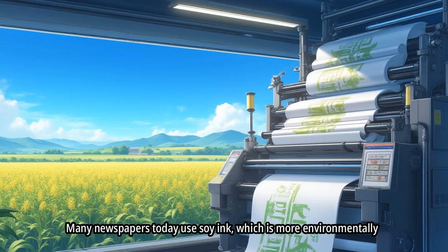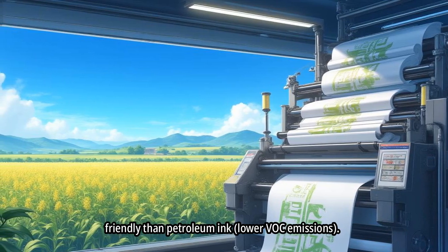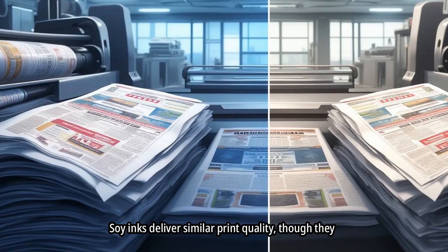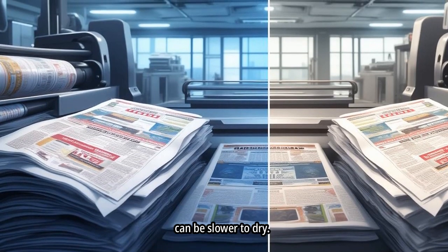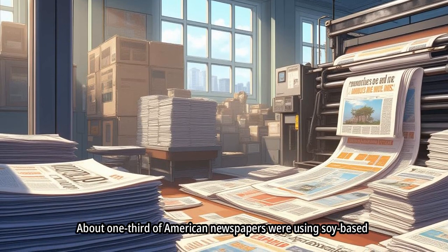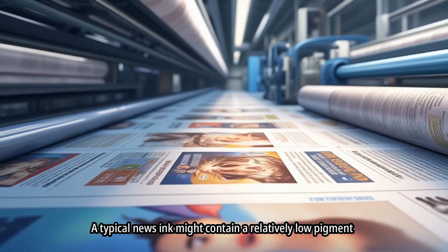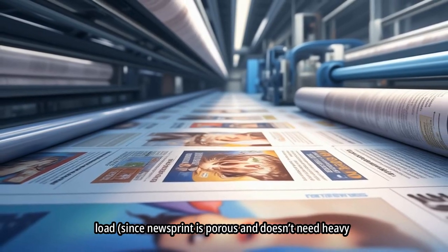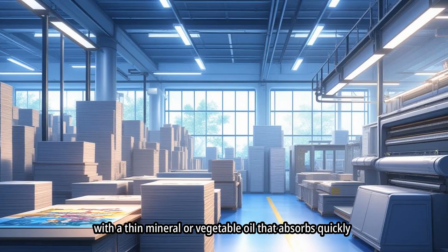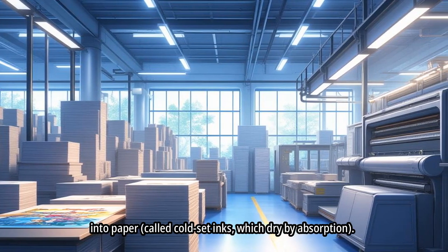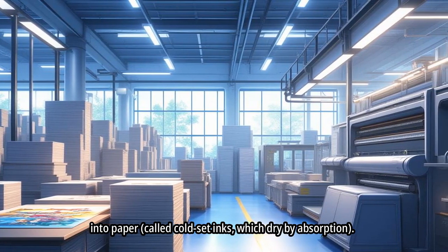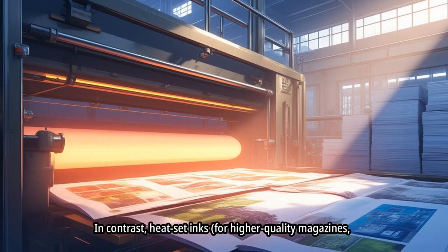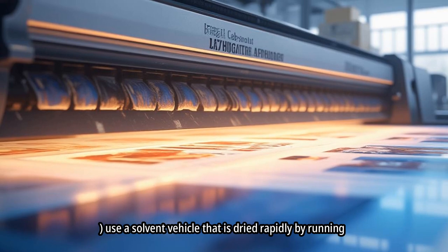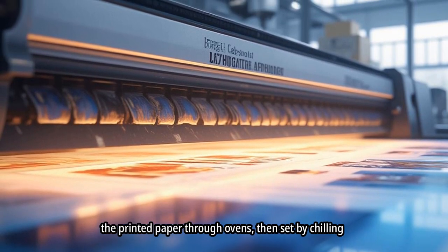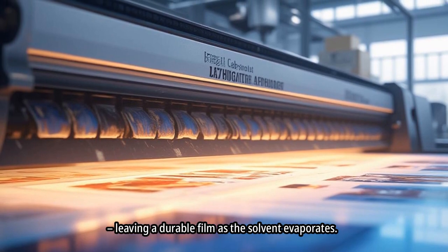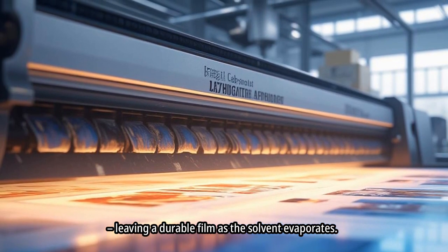Newspaper inks are a subtype of offset ink optimized for cheap, absorbent newsprint paper and high-speed printing. Many newspapers today use soy ink, which is more environmentally friendly than petroleum ink, with lower VOC emissions. Soy inks deliver similar print quality, though they can be slower to dry. About 1/3 of American newspapers were using soy-based inks by the early 2000s. A typical news ink might contain a relatively low pigment load, since newsprint is porous and doesn't need heavy coverage, with a thin mineral or vegetable oil that absorbs quickly into paper, called cold-set inks, which dry by absorption. In contrast, heat-set inks, for higher quality magazines, etc., use a solvent vehicle that is dried rapidly by running the printed paper through ovens, then set by chilling, leaving a durable film as the solvent evaporates.